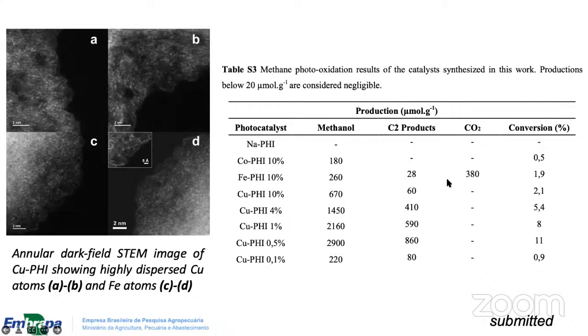It's important to compare both numbers. The comparison is interesting because the total oxidation of methane to CO2 is consuming more electrons than the partial oxidation. So the total amount of oxidation is comparable in terms of electron transference. But the conversion is much better for the copper, because in that case, we are doing this one to one for each molecule of methane.